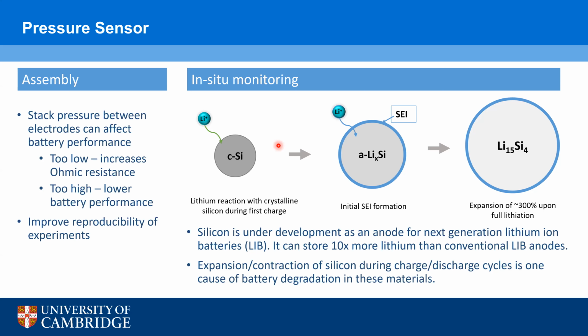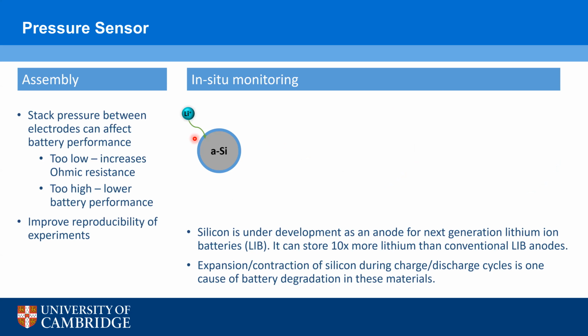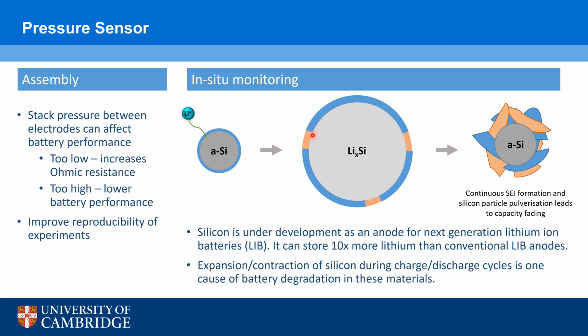So when you lithiate silicon in the first cycle, it can expand by up to around 300%. And at the same time, at low voltages, we get this degradation of the electrolyte that forms this SEI layer, or solid electrolyte interface layer, on the surface of the silicon. Then when we delithiate the material, the silicon shrinks back to not quite its original size. Then in subsequent cycles, when we relithiate the silicon, it expands again. This SEI layer cracks and exposes fresh silicon surfaces, where more electrolyte then reacts and forms a new SEI layer.